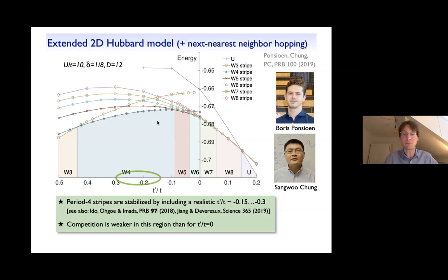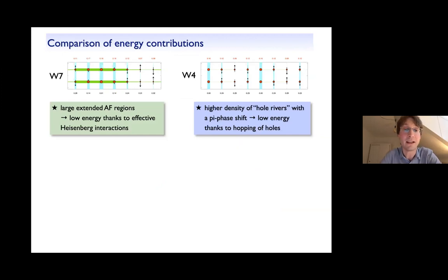Now let me try to give you some intuition why we get this shift in the stripe period. For this, let's compare the energetics of a long period stripe with a shorter period stripe. So here period 7 versus period 4. And let's have a look at the different energy contributions. What's nice about the period 7 stripes, the long period stripe, from an energetics point of view is that it contains these large extended antiferromagnetic regions with low doping. And that's good to minimize the effective Heisenberg interaction, right?